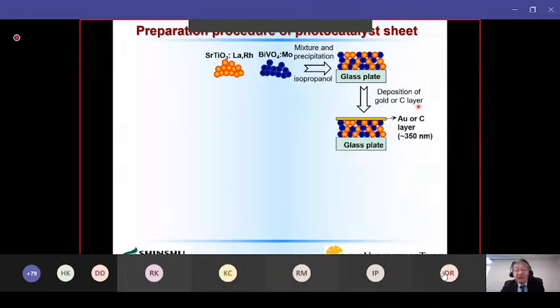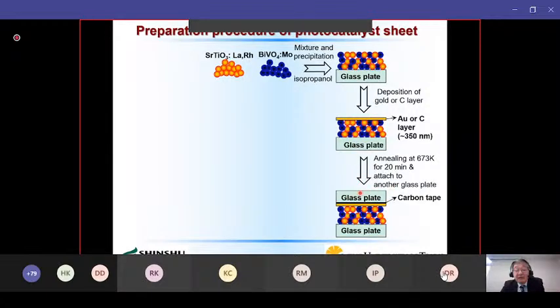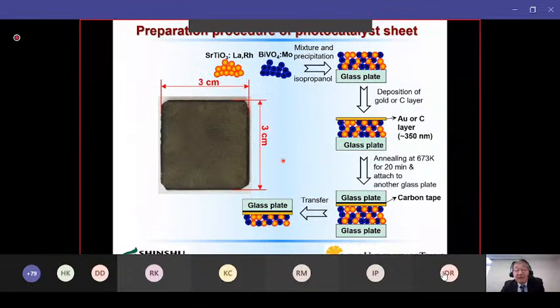Then after that, we deposit a conducting layer, in this case gold or carbon, by sputtering or evaporation. Then after annealing to fix this layer to the photocatalyst particles, we put another glass plate. In this case, this glass plate contains double-sided carbon scotch tape. So if we push and then peel off, we can get this kind of structure. There still remain some physically adsorbed particles.